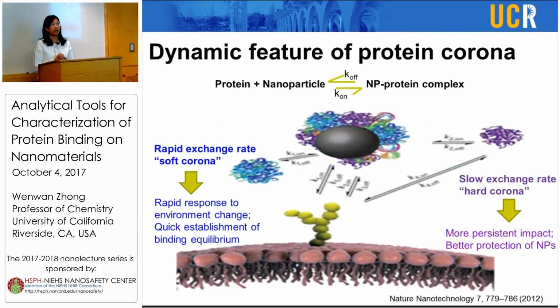So what do I mean by the dynamic feature of protein corona? Because we know that for protein adsorption, it could be forming a hard corona, which is very strongly attached to the particle with a slow dissociation rate. And then there is also a soft corona layer, which has a very rapid exchange rate for those proteins in the soft corona with the proteins in the environment. For this kind of soft corona, we believe the equilibrium can be established very rapidly, so they provide an initial protection effect to the particle when they enter the biological system.